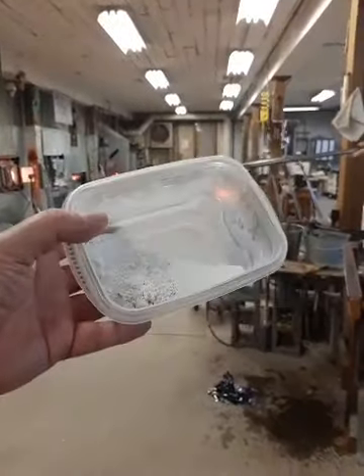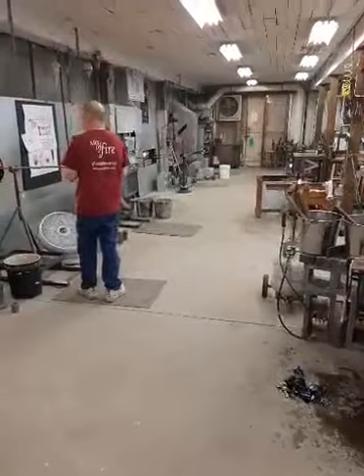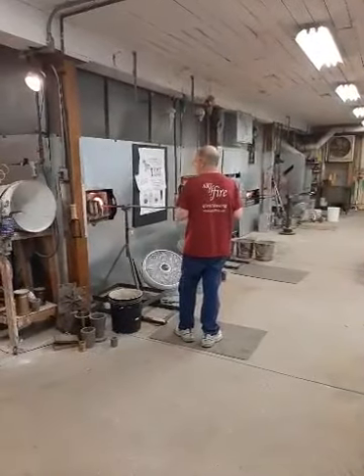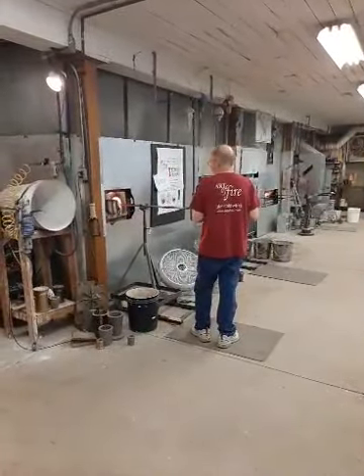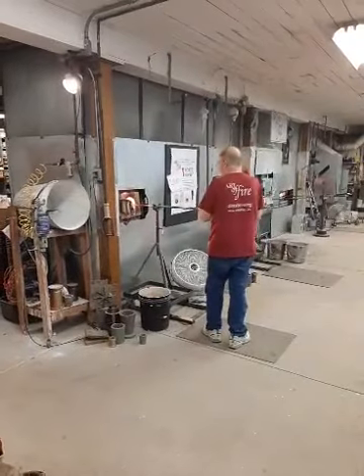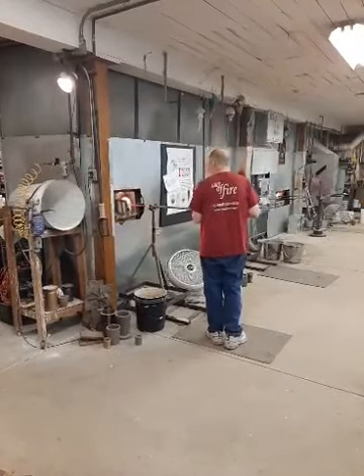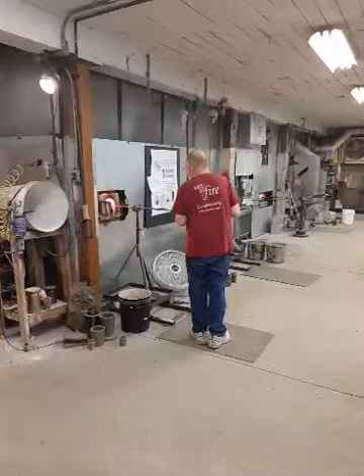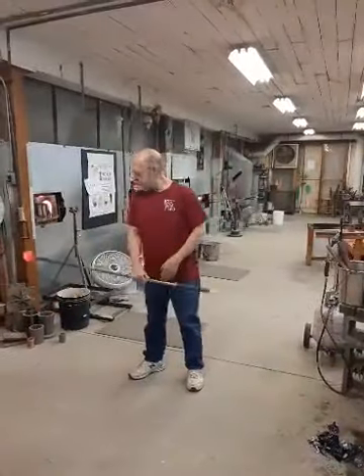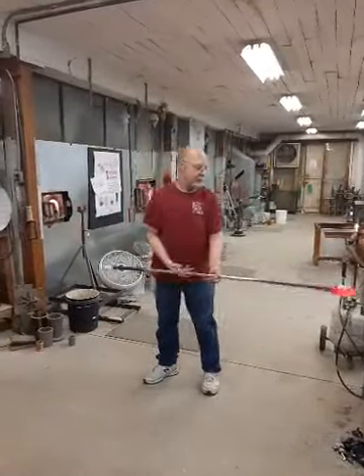This is what it looks like. This is the batch, the powdery substance which we mix up, and then that's shoveled into the furnace, and it melts down. It's not just a simple quick shoveling. Usually it takes place in a few stages, and we let the glass mound up in the middle of the furnace. Once it starts melting down, it starts to level out, and then we'll put another load in. After we get that all in there, it cooks, melting just like the witch from The Wizard of Oz. Then we fine it out by changing the temperature. That causes bubbles to rise to the surface, and the next day we've got glass.